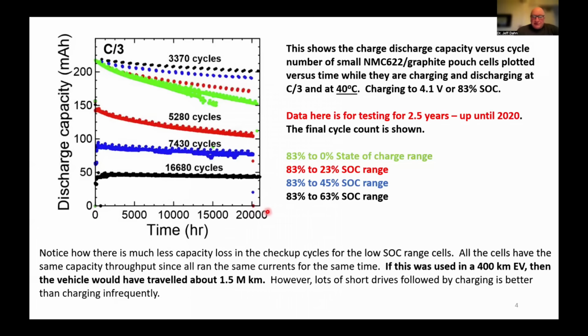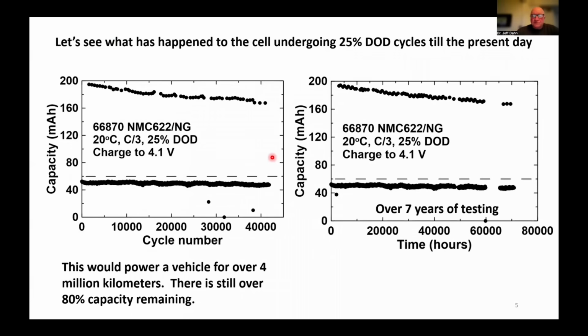I showed this data before, and this was data collected up to 2020. Anyway, the black cell we left on the chargers, and it's still running today, and I'll show you where it is now. So this is the cell that's running with a charge to 4.1 volts and a discharge to 63%, about a 25% depth of discharge range.